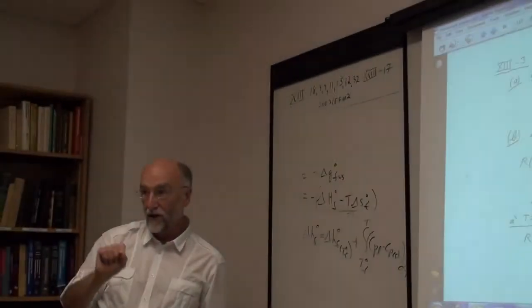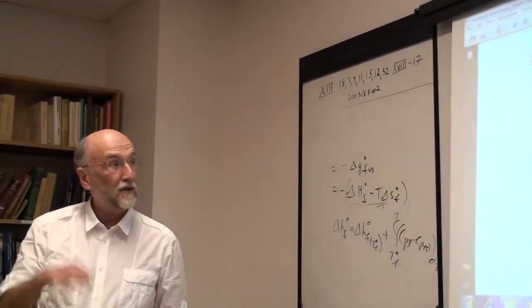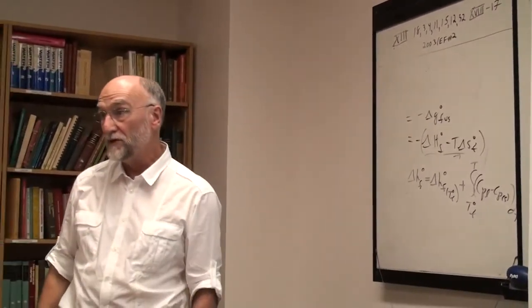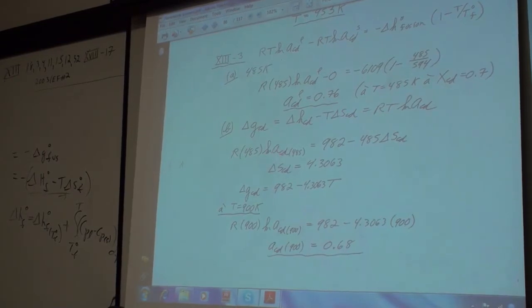Okay, so this gives you the activity of cadmium in the liquid. You're assuming that the solid solution has negligible solubility, so the activity is equal to 1 on the solid, so that term becomes 0. But the point here is that you can now solve this at other temperatures along the liquidus, and this gives you the activity of cadmium non-isothermally along the liquidus. The activity of cadmium at any composition varies with temperature. So this gives you the RT log activity of cadmium on the liquidus. That's part B, sorry. So this gives me the activity of cadmium is 0.76 at 485 degrees.